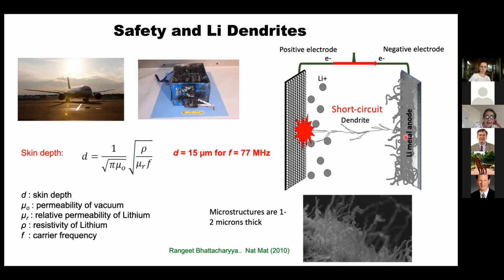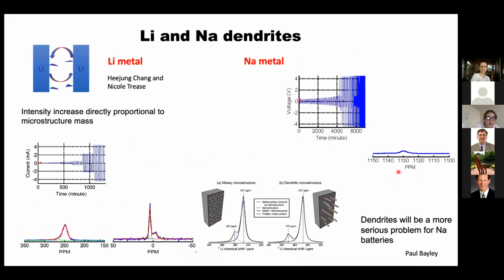And even graphite, and I'll show you this later, if you charge this too fast, you still form lithium dendrites. So what we recognized was that there was another problem with NMR, and I mentioned this when I talked about exciting your signal in the AAA battery, which is that you have a problem of skin depth in a metal. In a metal, there's only a limited depth that the radio frequency can penetrate. For lithium 7 that we use to detect our NMR, you can only detect about 15 microns at the frequency we're using. That means you can see a dendrite, but you can't detect the full volume of the lithium metal anode. So we used that as a way to track dendrites. And this just shows you a nice illustration of this, where we have a so-called symmetric cell.